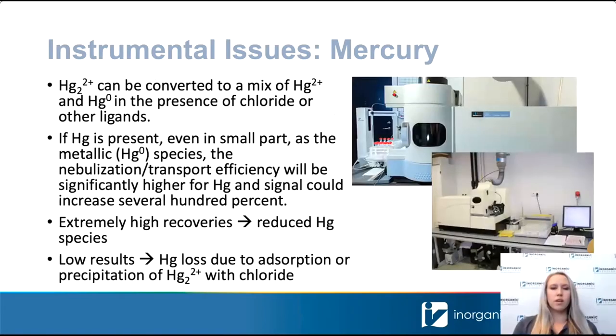Another issue that can occur with your mercury ICP analysis deals with the form of mercury in solution. So under reducing conditions, mercury 2+ can convert to the dimer, mercury 2 2+. This dimer can then disproportionate into mercury 2+ and mercury metal in the presence of chloride or another ligand. So if you do have this metallic mercury species present, that is volatile, and that's going to cause some pretty major issues when running on your ICP.